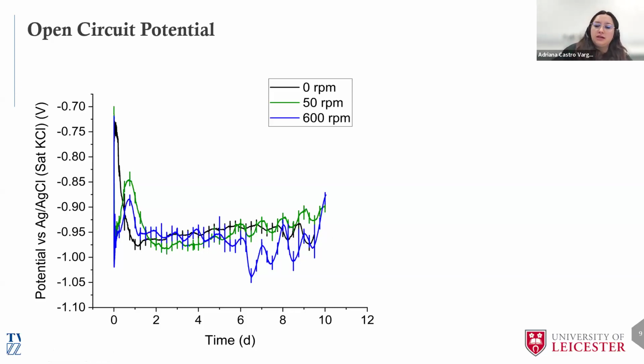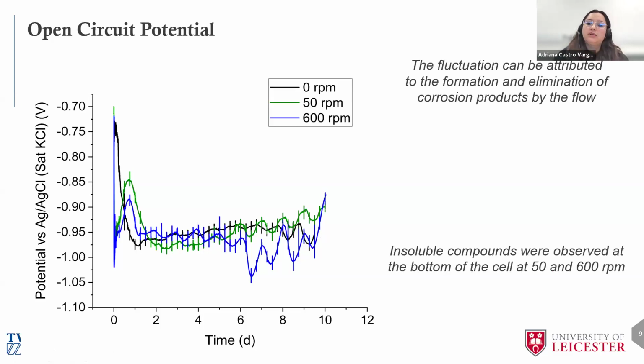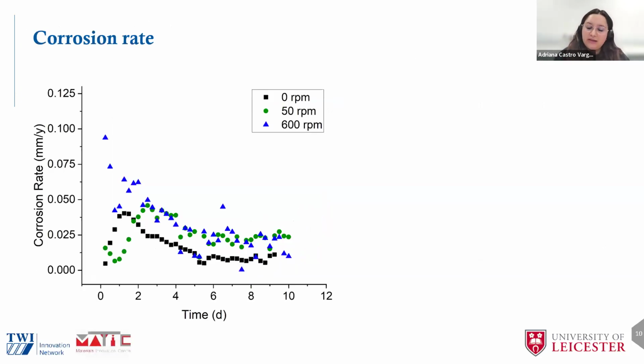However, at 50 and 600 RPM we can see fluctuation of the potential, which is unusual for stagnant conditions. We can attribute this fluctuation to the formation and elimination of these corrosion products or protective layers by the flow. Actually, in the bottom of the tank, we observe these compounds at 50 and 600 RPM, which means that they dislodge from the surface during the experiment. Finally, with this information, we calculate the corrosion rate. We can see that all systems at the beginning have a high corrosion rate because of the activation of aluminum. However, it's clear that at 50 and 600 RPM we got a higher corrosion rate.